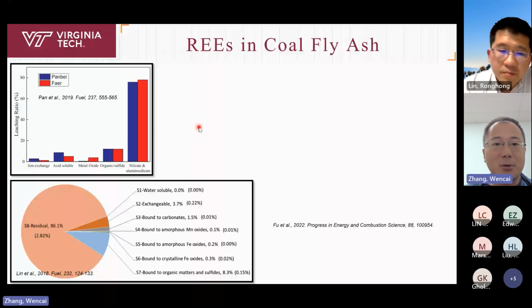So which means if the rare earths are in the glassy structure, if you want to recover the rare earths, you need to break the glassy structure. And as you know, the glassy structure is very stable, and you need very harsh leaching conditions to destroy the glassy structure. So this is the reason why REE recovery from coal fly ash is kind of difficult. This is because rare earths are in the glassy structure.